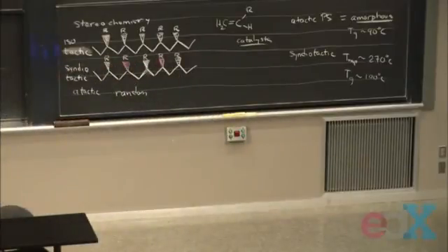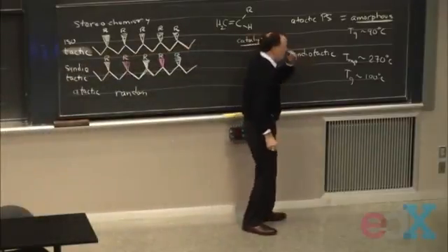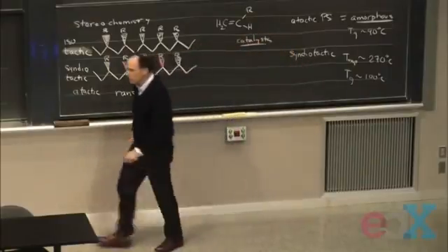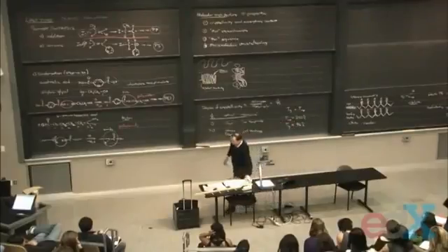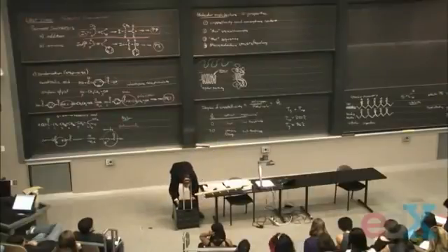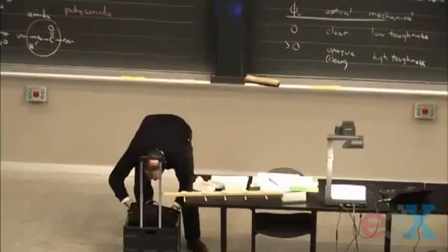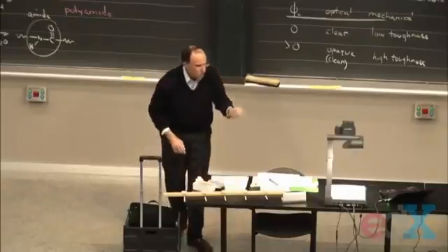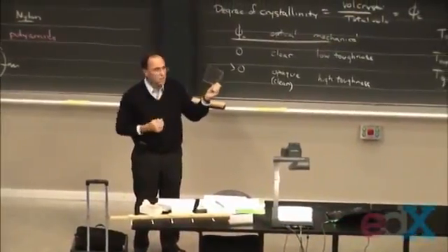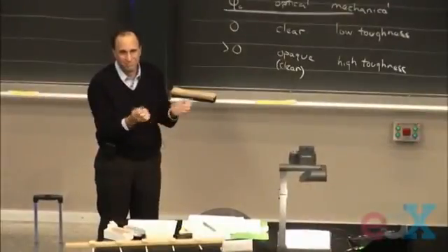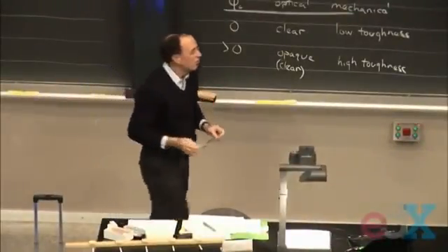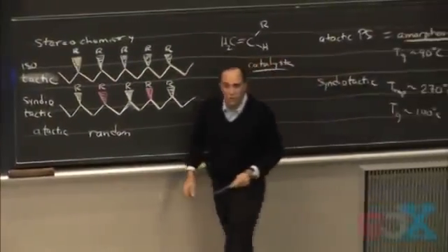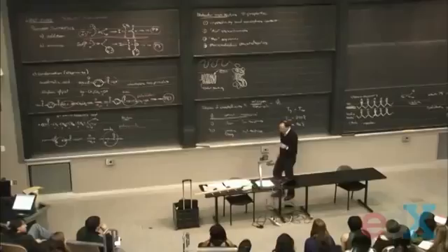Now, it turns out it's difficult to make syndiotactic polystyrene. It's rather slow, so it's made, but it's a rather expensive polymer. On the other hand, I scrounged around for some polystyrene things. Oh, here it is. So, jewel cases. What do you hate about jewel cases? They break, right? So it's a glass. Polystyrene is amorphous. You're below the Tg, and it does that. I just hate it.